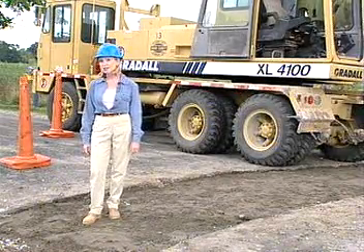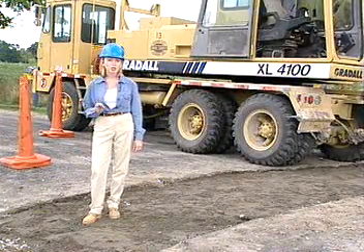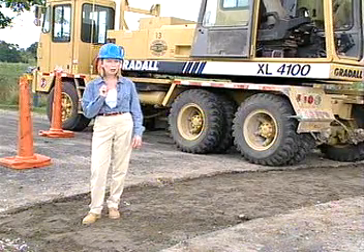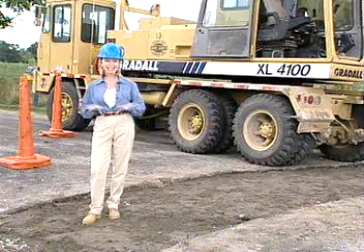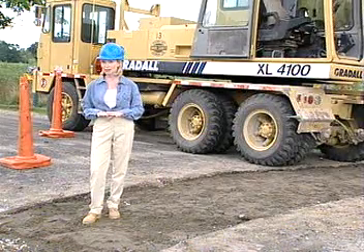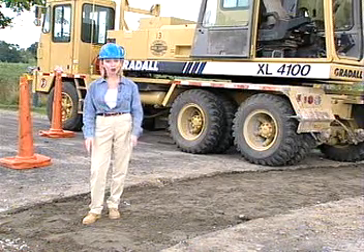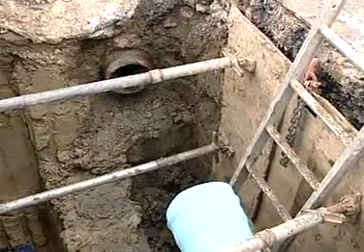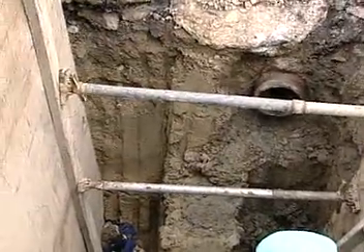Flowable fill does not settle. Once the mixture has undergone initial subsidence, now that's approximately 1/8 inch for every foot in depth while it's in its plastic state, further settlement will not occur. Since traditional compacted fill requires operating compacting equipment in the trench, the contractor must implement additional safety measures to ensure the safety of the workers.